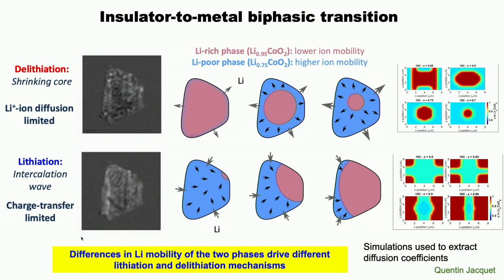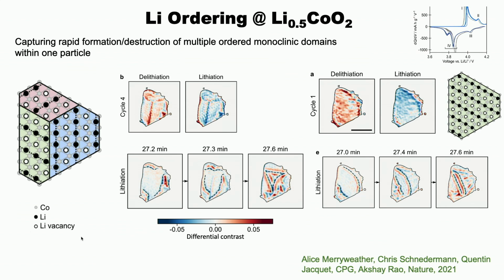But I now go in the opposite direction. I nucleate somewhere, and now I've formed a pink phase. That lithium isn't going to go through the pink phase. The only way that pink phase can grow is if it goes into the blue phase and adds to it. And so by very definition, it's really going to have to grow out in that direction. And in reality, it's the trade-off between the rate at which you can pull ions in and pull them out, the J, versus the relative diffusion coefficients of the two phases that explains this. And so just for completeness, this is this ordering transition I was telling you about. You form a phase, Li 0.5, where you have ordered vacancies, lithium, vacancies, lithiums.